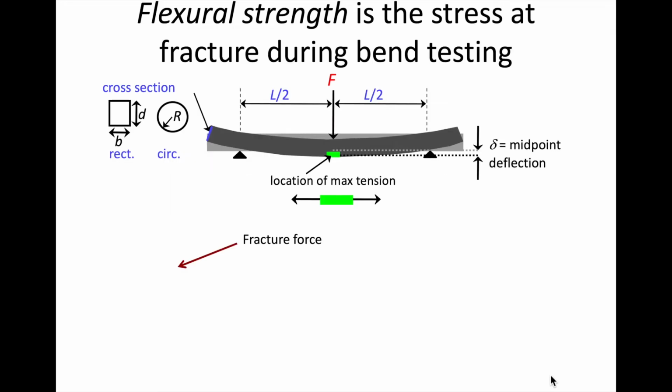All right, so we've talked about the 4-point bend configuration and some of the similarities and differences with 3-point. And so this diagram, this one specifically, is for 3-point. You can see the 3 contact points. But the point I'm trying to make here is that when it's in this configuration, we see differences in the stress state when we're in bending, in this flexure mode. As you can see here, the bottom portion is where it says there's max tension, and that would mean that the top is under compression.